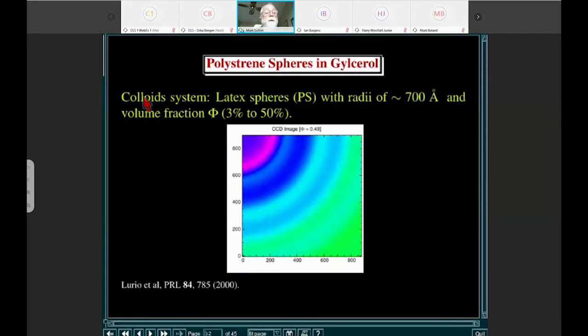So if we were to look at the scattering, we can dissolve various amounts of particles into the beam, and we're going to look at data from about 3% volume fraction to 50% volume fraction. And we're going to put the small angle scattering detector basically where the beam stop is up at the upper right-hand corner here. And so we're just going to look at one quadrant, because then we can see the largest range of Qs, and we know the scattering is symmetric, so the scattering at any of the other parts of the four quadrants will be identical to this.